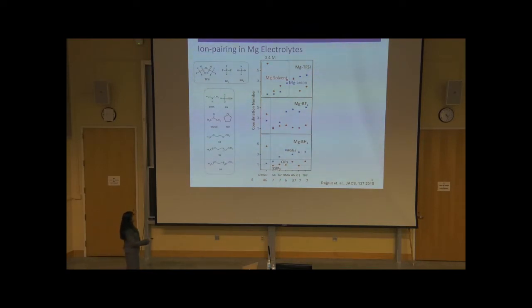On the other hand, we found that some of the low dielectric constant solvents, such as tetraglyme, which is G4 here, also result in formation of solvent-separated ion pairs. So here, the geometry of the solvent plays a very important role. The high donor density of these glymes and their flexibility to wrap around magnesium helps dissociate the cations from anions. On the other hand, some other high dielectric constant solvents, such as acetonitrile, fail to do the same because they interact through this weaker nitrogen atom and result in formation of ion pairs and aggregates.